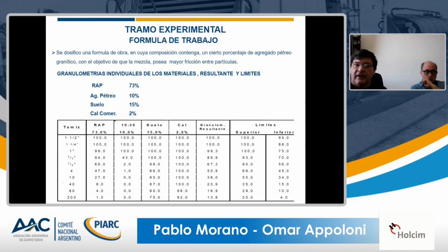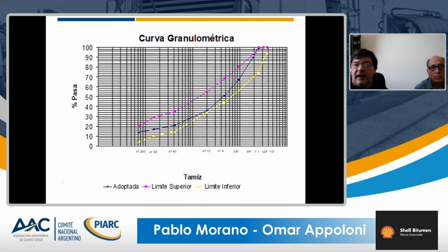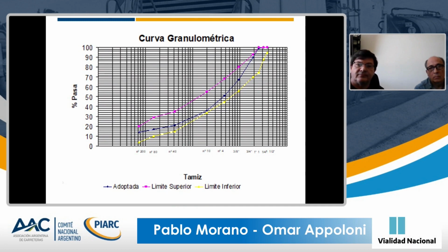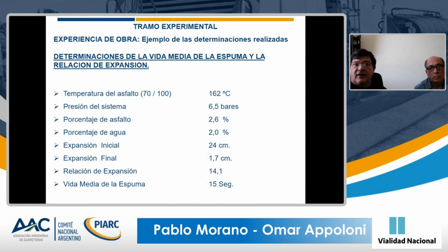What was used in this case was 73% of RAP. We added 10%, the soil that was 10% of fines. Soil was 15% and commercial lime was 2%, and the curve was within the limits of the manual. Here we can see the curve. At the bottom is with a contribution or more fines added and then more coarse added.